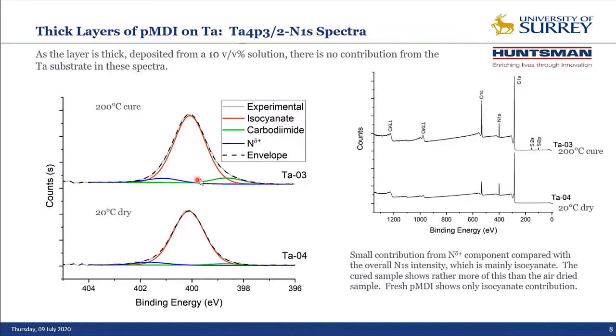But if you cast your mind back to the nitrogen component where we saw this, and we saw some isocyanate along with the tantalum, very thin film, this was about 40, 50, maybe 60% of the intensity of the isocyanate group. So the way we interpret this is the nitrogen delta plus is there as a result of self-association in the PMDI itself, but it's also indicative of donor-acceptor, sometimes called acid-base interactions, between the tantalum oxide and the PMDI.